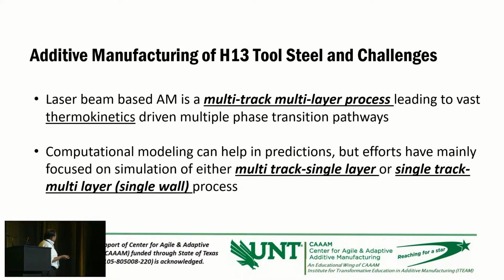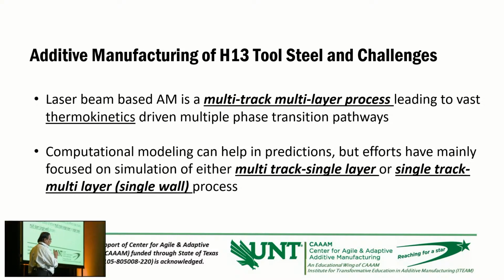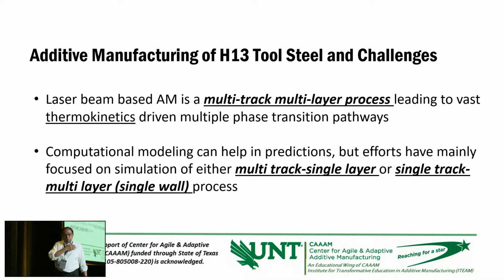And in addition to these extreme thermophysical conditions, the AM process becomes more complex because, as you know, the laser being a very small beam diameter, you can only fuse a small portion of the material. So with that, you have to create a layer by putting multiple tracks in one layer. And then you have to deposit several layers to create a component of reasonable size and shape. So it is a multi-track, multi-layer process that creates a very complex thermokinetics in the process. And thus the process becomes very difficult to monitor, or to control, or to get an understanding of the process.